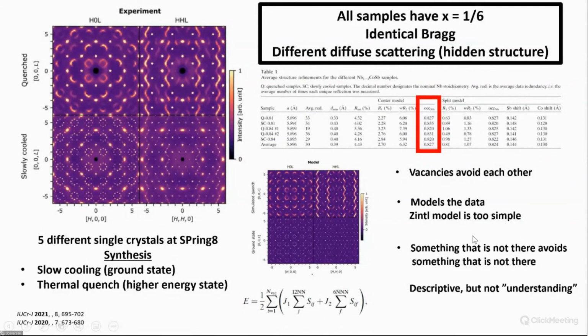So what these things say, first of all, again, please do not use the Zintl model for this, because all the structures have x equal to 1/6, they do not have 20% vacancies. The structure really wants to have the vacancies avoid each other. It's not about the stoichiometry. And the second thing is you can say, okay, you now know that something that's not there avoids something that's not there. That's really not chemical understanding. It's just purely describing the diffuse scattering.